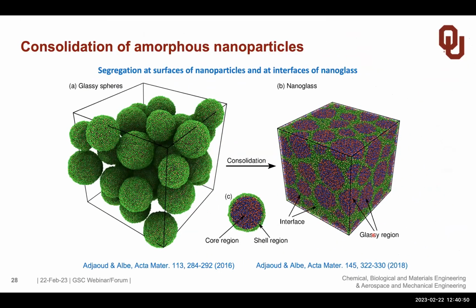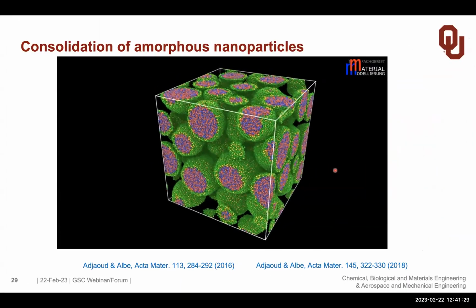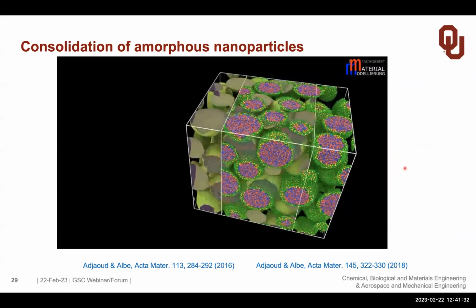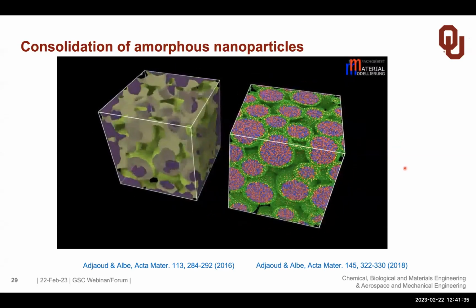But this is a simulation which I borrowed from a group at the TU Darmstadt, Professor Albe, and they have done a molecular dynamics simulation of this process of consolidating particles. First of all, they have found that on the surface you have an enrichment of one element and a depletion of that element on the inside. So once you start to consolidate these particles, you form interfaces, which are shown here in green, where the composition is different, but also the structure and the free volume. And in order to show you this process of the consolidation, I show you this little video, and I think it's almost self-explanatory.